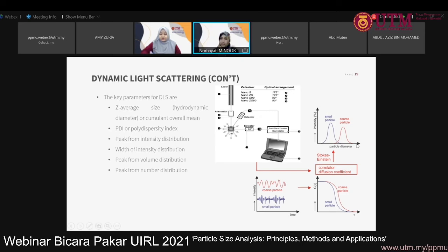You can get the graph, for the small particles near the y-axis, and the coarse particles at the back. This is what we call the hydrodynamic diameter, or the cumulant overall mean, because you can imagine in your sample you may have billions of particles, so they accumulate everything, make an algorithm, and give you the mean of your total sample. From that result, you know the PDI, or polydispersity index. This is also important in your study. The PDI shows how well your products distribute in your formulations, along with the peak from the intensity distributions, the width of the intensity distributions, and the volume and number distributions. This is some of the information that you can get from dynamic light scattering results.